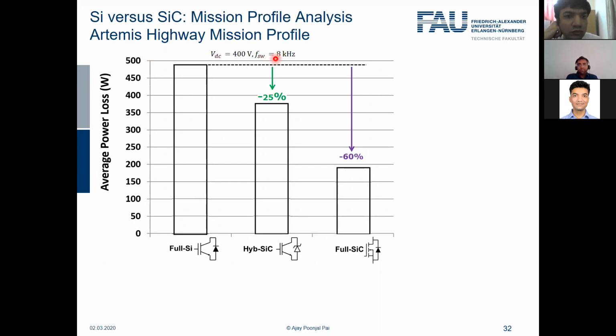These are the boundary conditions here. This is a 400 volt system, like I said, this will be the focus. The switching frequency is 8 kilohertz. And now we see the hybrid silicon carbide module, right? This has 25% lower losses because with the silicon carbide diode, the reverse recovery losses are reduced or almost disappeared even. And with the full silicon carbide module, we see the power losses are reduced by 60%. So this is what we calculated.